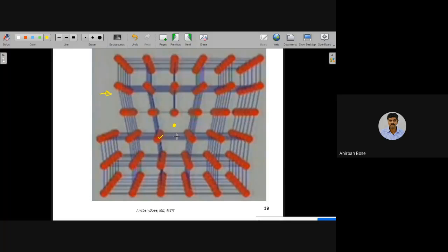This is the region. Actually it is a line. If you observe, these atoms are now closely spaced. If you compare with the region far away from this, the distance or the periodicity between the atoms, you will observe that they are now closer. Okay, so these atoms are now under compression, if you compare with respect to the other regular atoms, the perfect part of the crystal.